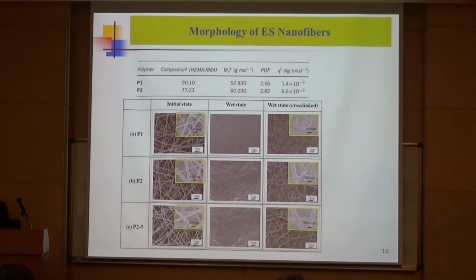So the next slide shows you the SEM images of the morphology of electrospun nanofibers, which were prepared using two copolymers with different molecular weight and one blending of P2 copolymer with 5% of fluorescent sensing compound. For the spun nanofibers, we observe the average diameter for P1 nanofiber was around 250 nanometers. But for the P2 and the P2-5 blending nanofibers, the average diameter was around 500 nanometers. So the smaller diameter for P1 nanofiber could be attributed to its lower molecular weight and thus lower viscosity of its polymer solution.